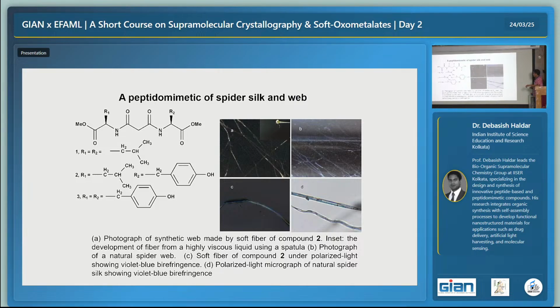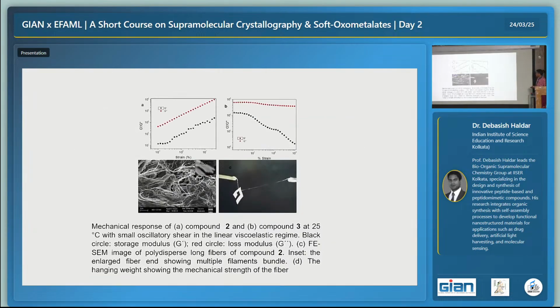And this is the natural spider silk on my window pane, and this is what we have prepared using a spatula, or you can even use an injection syringe, and you can do that below 20 degrees centigrade. We also studied the morphology and optical properties of the compound using a polarized optical microscope, where we saw that both the synthetic material and the natural one show the same behavior. We also tested the rheology, and the morphology by FESEM, field emission scanning electron microscope.